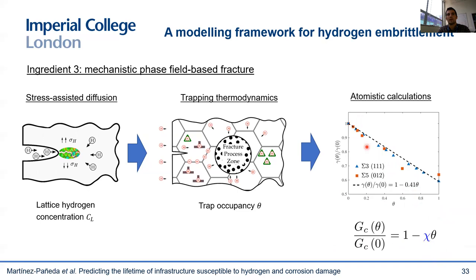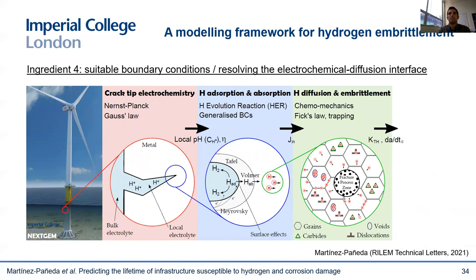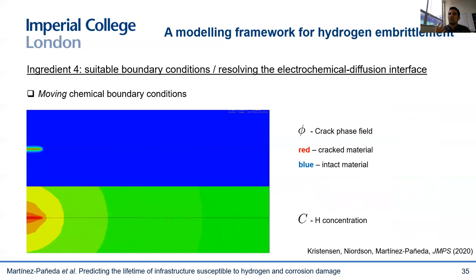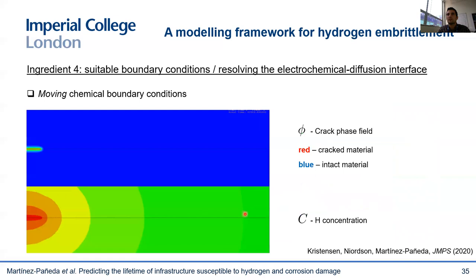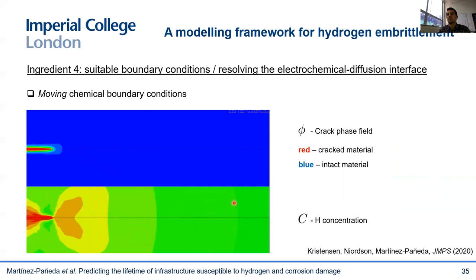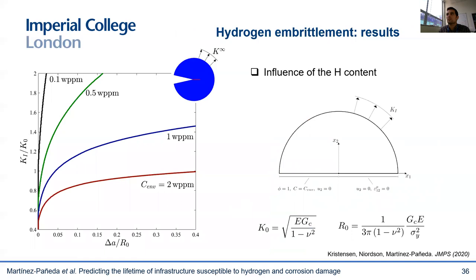There is one last ingredient: the boundary conditions of the crack phase. We have been working on resolving the electrochemical diffusion interface to properly quantify how much hydrogen is entering the sample. We have also developed suitable boundary conditions to capture how the environment follows the crack as it propagates. If you have a crack propagating in a wind turbine monopile, you would expect seawater to immediately occupy the space created by the new crack surface. This can be achieved using a penalty approach, and you can see the concentration from the environment nicely following crack growth.